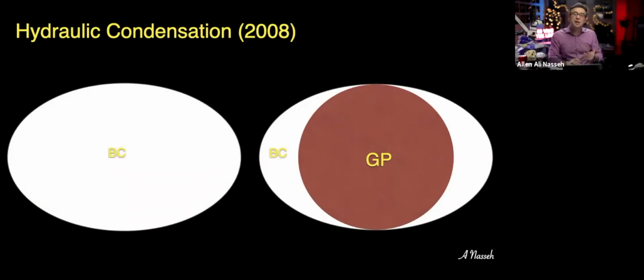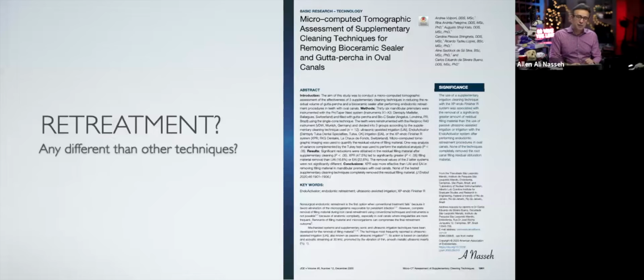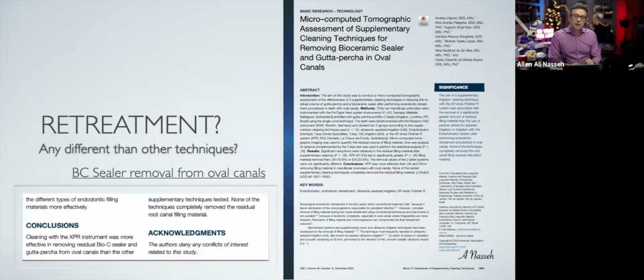even though you can, and maybe in a central incisor with trauma, you want to fill the whole canal with the bioceramic, you certainly can, as we used to do those with MTA many times, with cases of barrier technique and one-step apexification. But for the most part, you always want to have a gutta percha in the center so that the tooth can be retreatable. So we don't want to do this if we can avoid it. And retreatment has now been shown through a number of studies to be no different than any of the other techniques, with excellent and efficient revision available and possible.